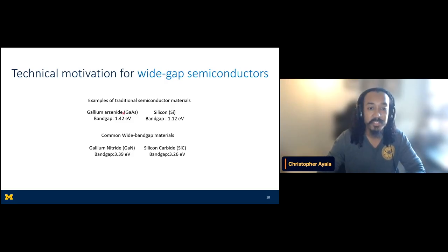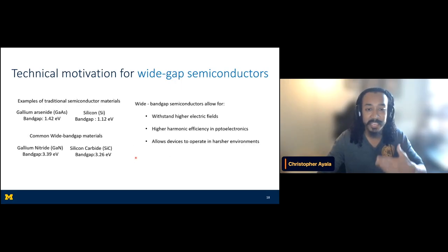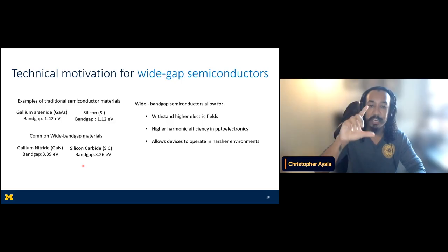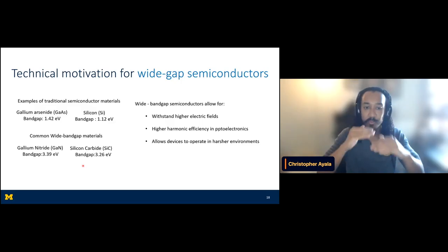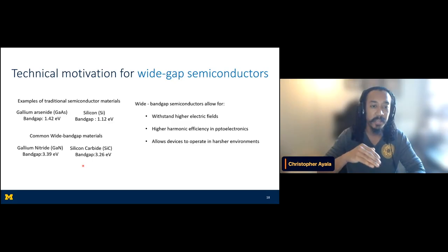The main difference between these two is the band gap. As you can see here, most of these materials will have a band gap of greater than 2 eV. What does this increased band gap allow us to do? Well, these materials can now withstand higher electric fields. They are able to generate higher harmonics in more efficient ways, because you're allowed to grow the material in whatever format you would like, which you'll see on the next slide. And these devices are allowed to operate in harsher environments, and in that case, it's working at higher or lower temperatures than you normally would imagine.